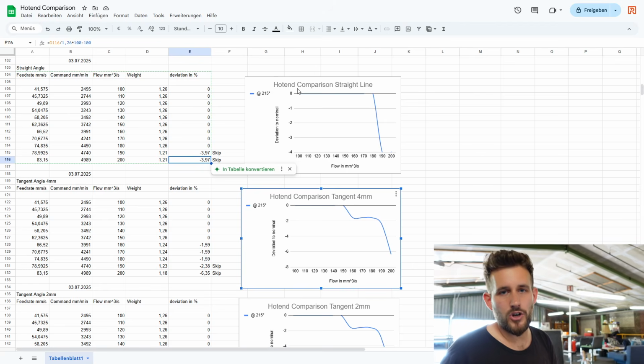So full disclosure here, most of the manufacturers of hot ends will give you just the best case scenarios for their flow ratings. So we could go, and I did that yesterday, up to 250 degrees, and all of these hot ends will add 50 cubic millimeters of flow, topping out at 220, 230 or something. But we want to have normal scenarios. We don't want to push material to the absolute limits and overcook it for certain regions where we don't ask of that volumetric flow and the filament stays longer in the heat zone. We don't want to have that.